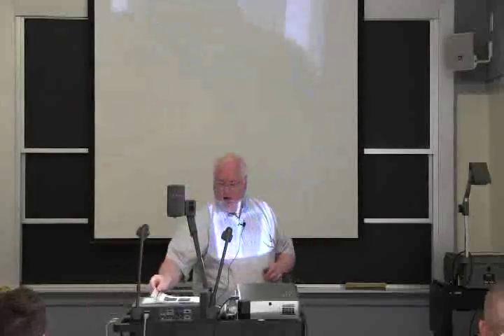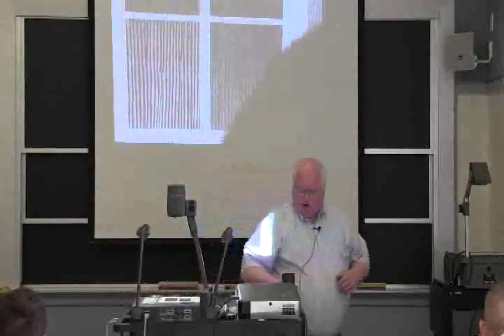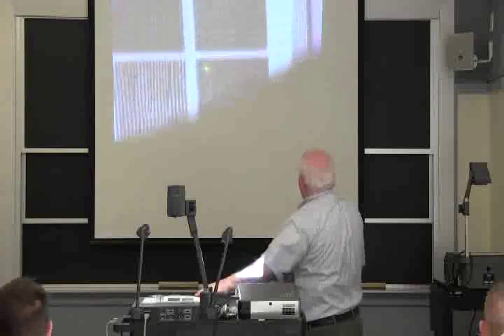Flemings actually showed you could grow all kinds of structures off the equilibrium structure. This is a composite structure where you control the cellular growth. On a transverse section you see the grass, looking at the top of the grass, one phase over another. On a longitudinal section, you get stringers like this. The paper is called Growth of Composites from the Melt, and you're growing it in a gradient furnace just like these turbine blades.